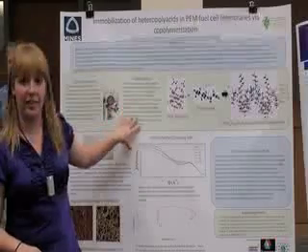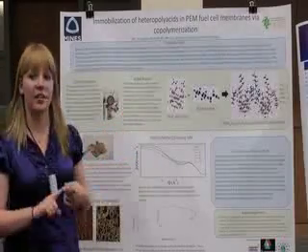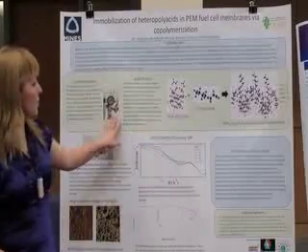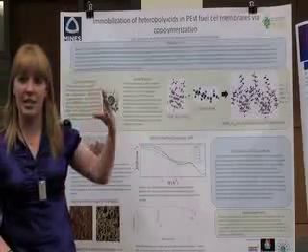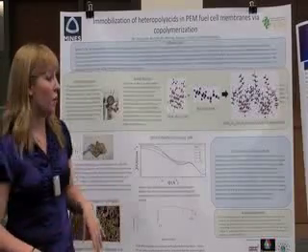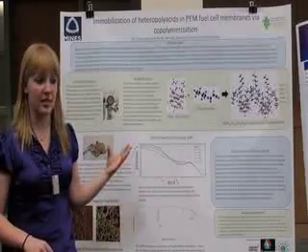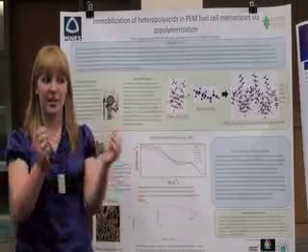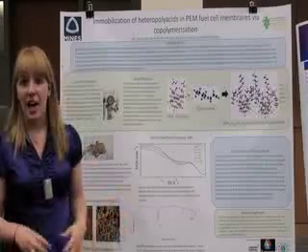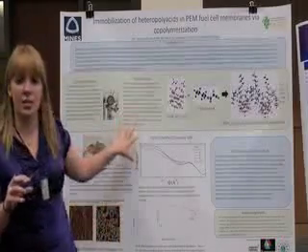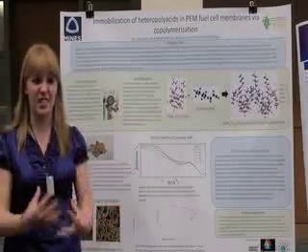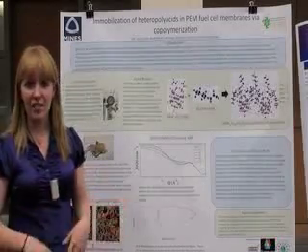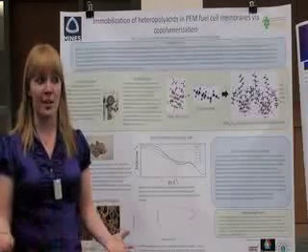So this was how I did the ethylene polymerization. I had ethylene gas with a liquid heteropolyacid, and I put them into this bomb reactor that keeps it at a high pressure and a high temperature in a closed system. So over a period of time, the double bonds in the heteropolyacid and the ethylene break and form a long polymer. After taking this ethylene mixture out of the bomb, you get a really sticky, goopy mixture, not a membrane. You have to make a membrane from that mixture.